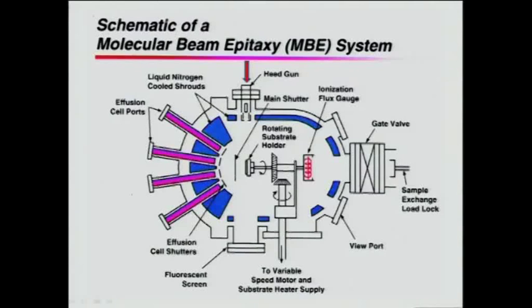And this is the schematic looking down from the top of the MBE system, the stainless steel chamber pumped to ultra-high vacuum, and the blue area shows the liquid nitrogen-cooled shroud surrounding the whole chamber to give us a very ultra-high vacuum. And then these are the effusion cells. The sample is mounted in the center, rotating continuously, giving us the uniformity we need. And the thing I want to point out here is this.